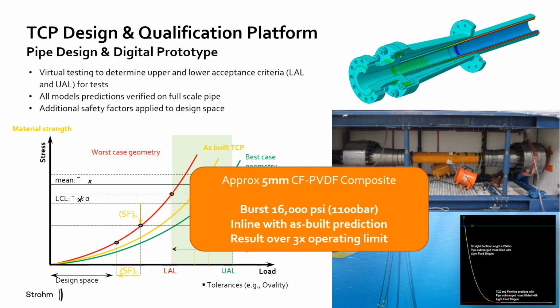To give you an idea of the accuracy of our digital prototype, and bear in mind we had never physically made that particular design before, the burst pressure was 1,100 bar, and more importantly, within a few percent of the prediction. Confidence is key, as is safety, and when we consider the safety factor for this design, the burst pressure was more than 3 times the operating limit, making this an extremely capable and extremely safe pipe.